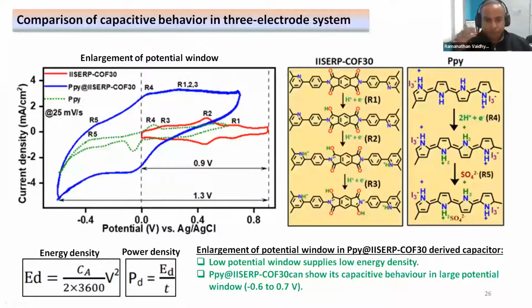And importantly, the electrochemical activity. Here is the cyclic voltammetry of the neat COF shown in red color. Then we see the cyclic voltammetry behavior of the neat polypyrrole grown as a control in the green dotted CV. The comparison is with the blue cyclic voltammetry curve, which is for the composite material. You can see there's a drastic enhancement in the current of this composite, which is potentially due to the strong interaction between the both.